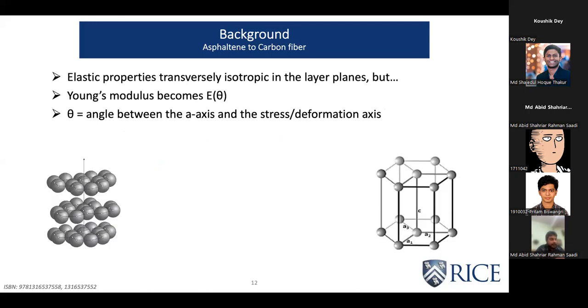For example, if you have a graphite-like structure and you take one graphene sheet out of it, the mechanical properties, or the elastic properties, are basically isotropic in nature. That means if you measure the properties from any angle, you're going to have similar mechanical properties in that plane. But when you have a graphitic structure and you measure the mechanical properties along certain axes, for example, here the Young's modulus becomes a function of theta. Here, theta being the angle between the basal axis A and the stress axis,